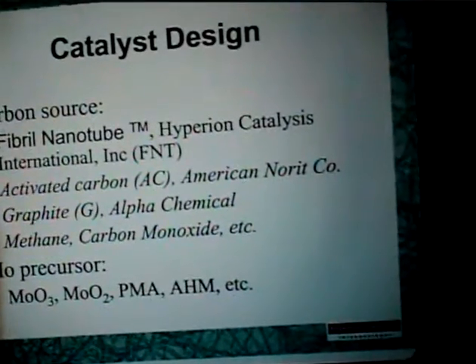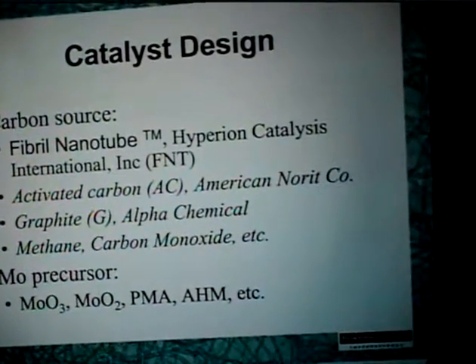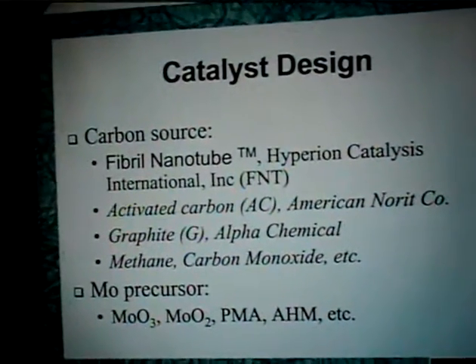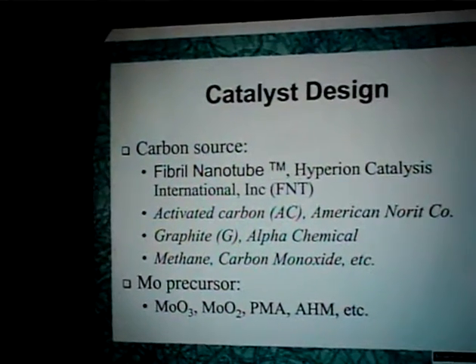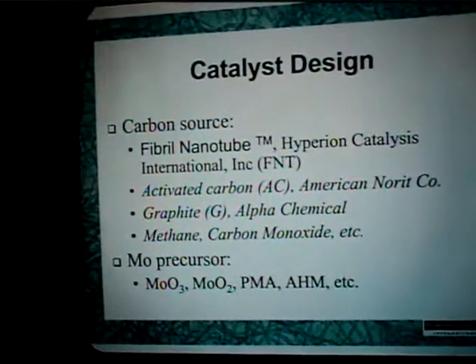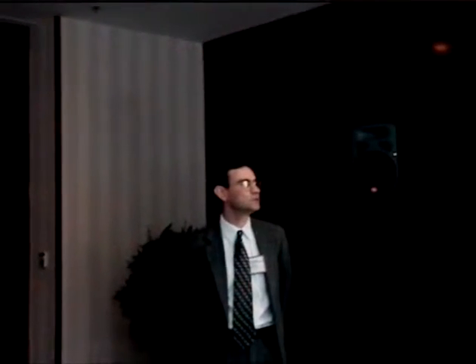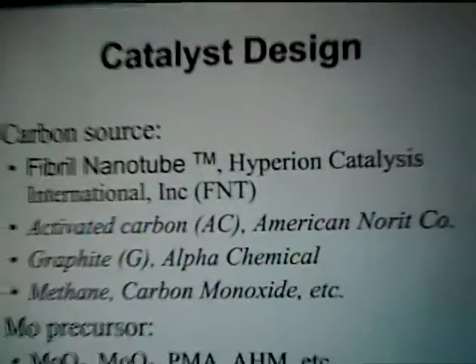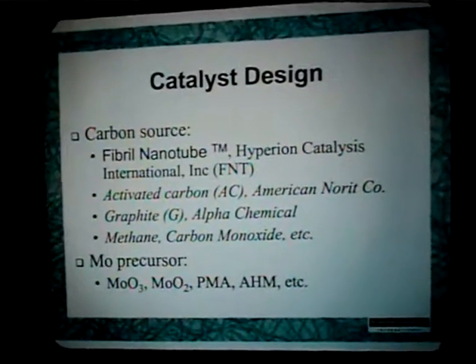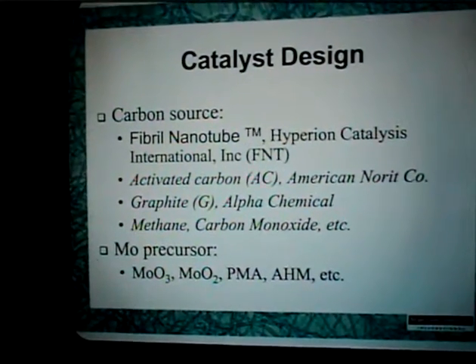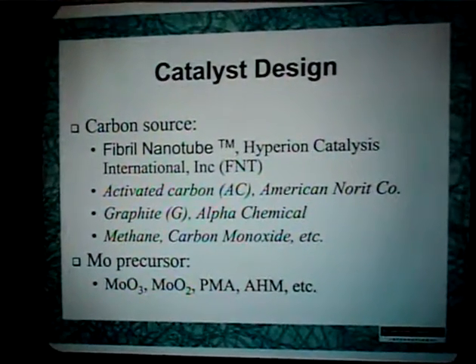For comparison, we tried other catalysts. There is what Hyperion calls the fibril nanotube, which we abbreviate here as FNT. As I told you, they make these in hundreds of tons per year. As far as I know, this is the only company that sells those materials commercially. We also used activated carbon and graphite as a carbon source. Sometimes we just take the molybdenum oxides, pass a gas carbon source over them, and prepare those materials unsupported for comparison. For the molybdenum precursors, we used the oxides, ammonium-based ones, and phosphomolybdic acid. So we used a number of precursors.